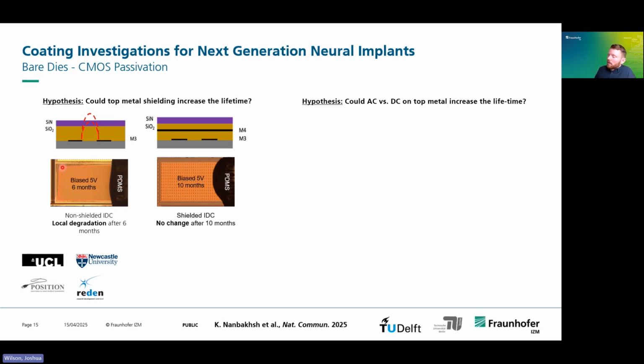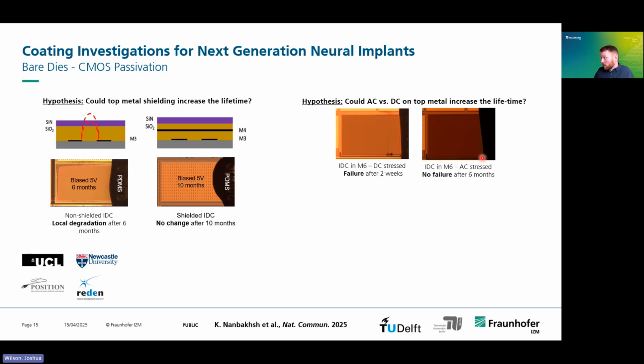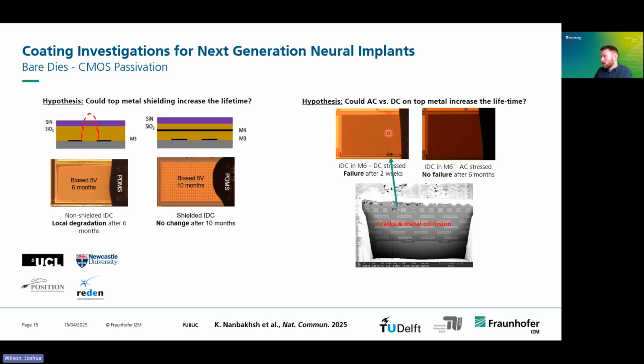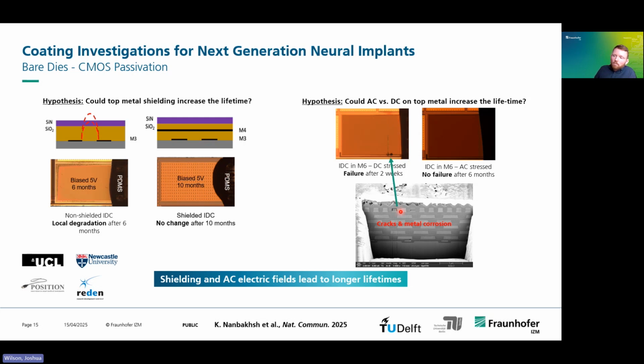Another hypothesis was that, okay, this is DC. What we already saw is that the failures were signal dependent. What about if it was AC? And what we see again there is that there is no failure. So if we use AC in the top metal layer rather than DC signals, we don't see any failure. And actually, you see in the DC stress device here, the failure was very fast. After 2 weeks, there are cracks in the coating, and the metal is corroded. So a conclusion would be that the shielding and AC electric fields in the top metal layer can lead to longer lifetimes of these ICs.